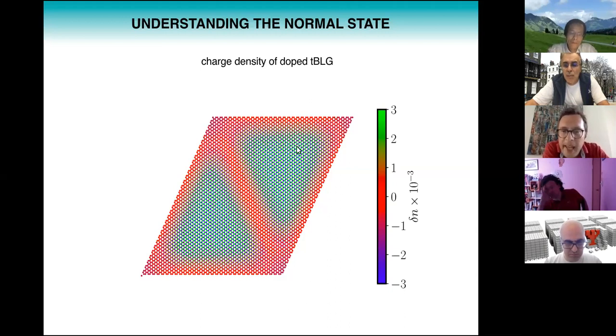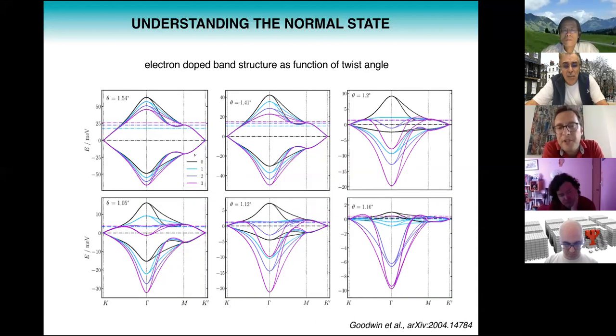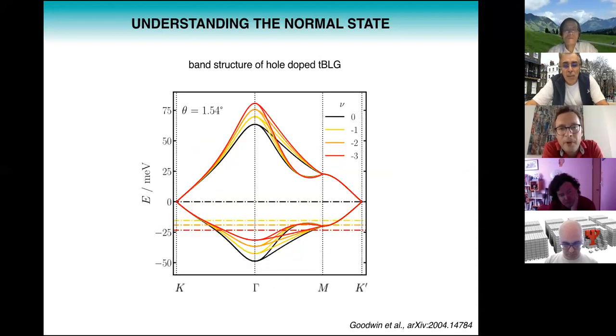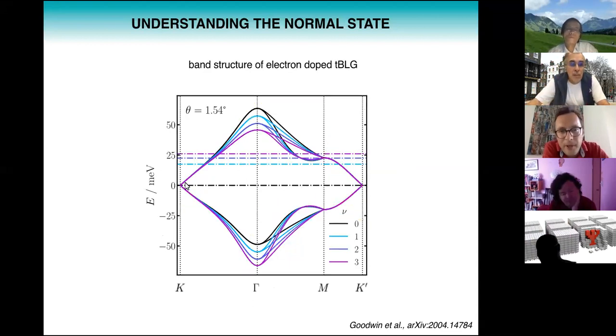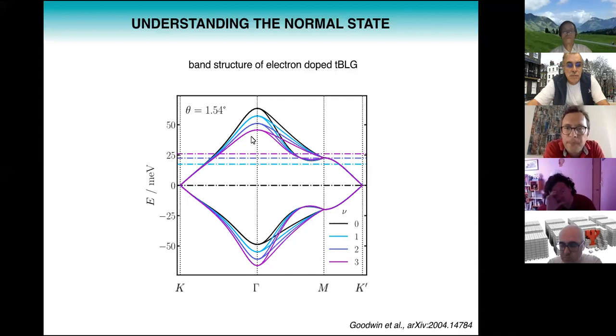What we know is that these carriers localize in the AA regions. So there's a large charge density in the AA regions, and this charge density creates a Hartree potential. This Hartree potential will push up any charge that is localized in the AA regions. And that's precisely what we see here. So the states at K are localized in the AA regions, and they are essentially pushed up relative to the states at gamma, because the states at gamma are not localized in the AA regions. They have a ring-like shape. So by adding these extra electrons, we create this repulsive potential in the AA regions that pushes up states there, and that leads to this deformation of the band structure and the flattening of the conduction band.